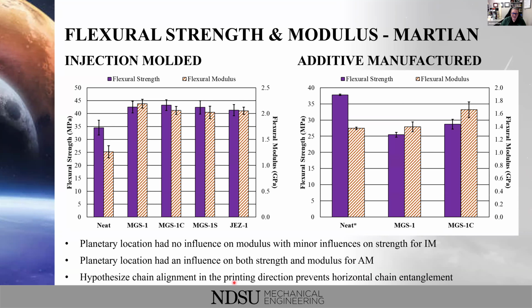And then again, that chain alignment in the printing direction is coming into play here with our polypropylene. The neat specimens themselves have higher properties when you additively manufacture with them, which is not what we expected to see at all.